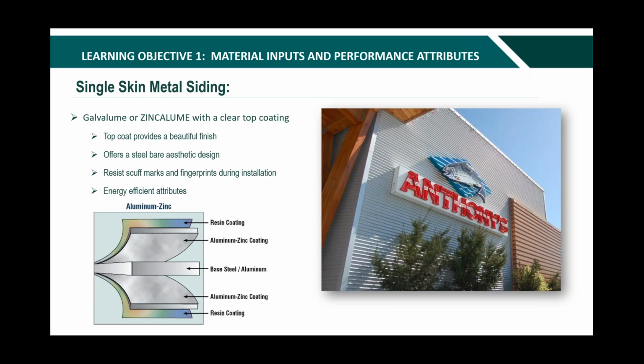Galvalume or Zincalume with a clear top coating provides a beautiful finish. It offers that bare steel aesthetic design while resisting scuff marks and fingerprints during installation. And then it does have some energy efficient attributes. So the base steel or aluminum, again, as far as the bare Galvalume or Zincalume is concerned, it's the steel and then the zinc coating and then a top resin coating, which is clear. And with this particular product, the resin coating is on both sides, so you have the same look on either side of the metal.